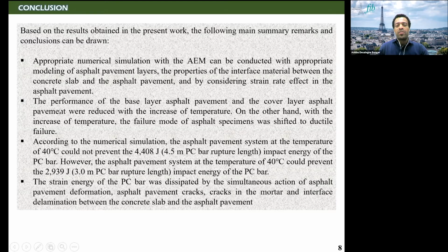Second, performance of the base layer asphalt pavement and cover layer asphalt pavement were reduced with the increase of temperature. On the other hand, with the increase of temperature, the failure mode of the asphalt pavement shifted to ductile failure. And according to the numerical simulation, the asphalt pavement system at a temperature of 40 degrees centigrade could not prevent 4,400 Joule impact energy. On the other hand, a similar simulation with around 3,000 Joule impact energy was effective.